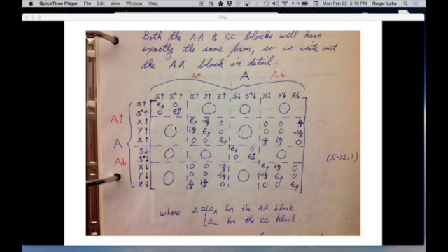And so you know how levels tend to push apart when they couple. So out at the X, if you have this extra S orbital up here that's above everything, and it couples to the P, then it pushes that down and gets it about the right energy where it should be. So this represents the S star. You'll see this in quantum chemistry codes. They always represent it as a star. So it's an unoccupied state from the next shell up.